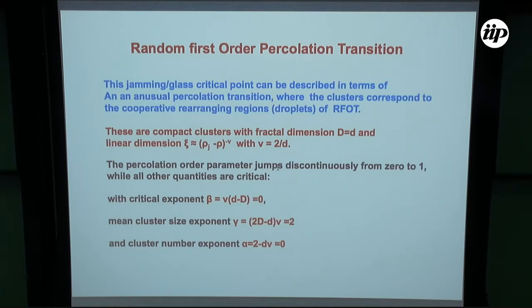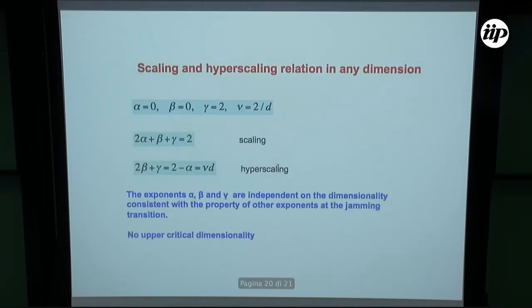but this is a sort of mixed order percolation, because the order parameter jumps discontinuously, but the other critical exponents, as we have already seen, are such that psi diverges with an exponent nu, and the mean cluster size exponent is given by 2 times the fractal dimension minus d times nu. If you insert nu and capital D equal to d, you get gamma equals 2, and alpha, the cluster number exponent, equals 0. So in conclusion, we get the exponents alpha equals 0, beta equals 0, gamma equals 2, and nu equals 2 over d.